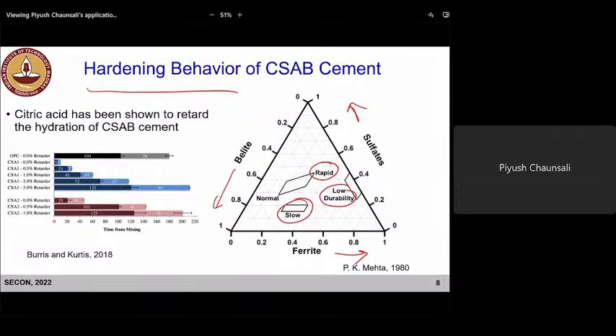So basically this gives you an idea. Depending on this, if you have a composition, you can get an idea about its hardening behavior, whether it will have a normal hardening behavior, whether it will be rapid or slow, and accordingly then we can decide which admixtures to use. Let's say in this case, left side, this bar chart shows you citric acid was used to retard the hydration. So sometimes what happens, the hardening is very fast, and normal admixtures which we use in Portland cement do not work. So citric acid in this case has been shown to retard the hydration. So it gives us some time to work with this concrete, which contains CSAB cement.